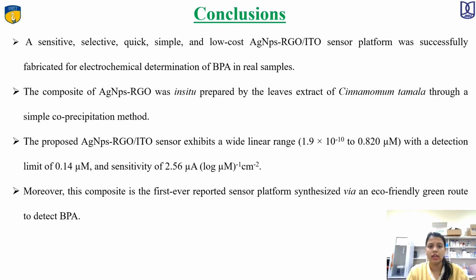And at last, I would say in conclusion that a sensitive, selective, quick, simple, as well as low-cost Ag nanoparticle reduced graphene oxide sensor platform was fabricated using the electrophoretic deposition technique on indium tin oxide glass substrate, and this composite was prepared in situ by the leaf extract of Cinnamomum tamala through a simple co-precipitation method, and it shows wonderful results in terms of wide linear range, detection limit, as well as sensitivity. Also, it is the first reported sensor platform synthesized via an eco-friendly green route to detect BPA.